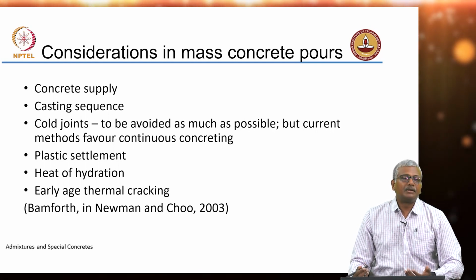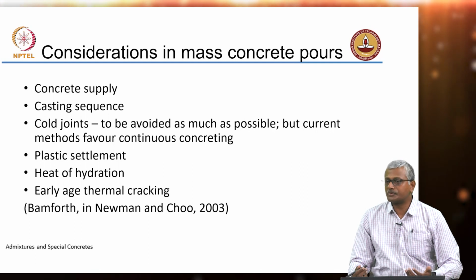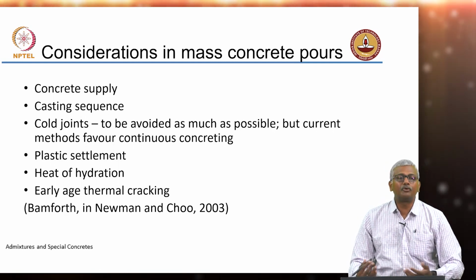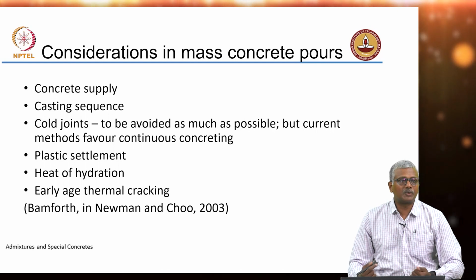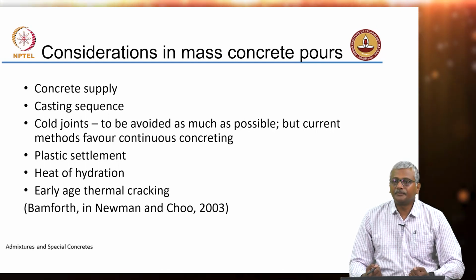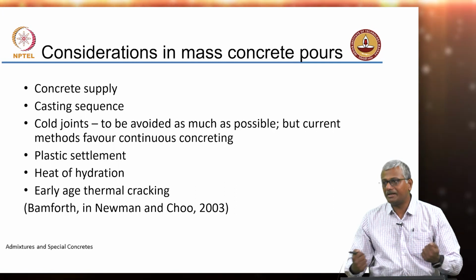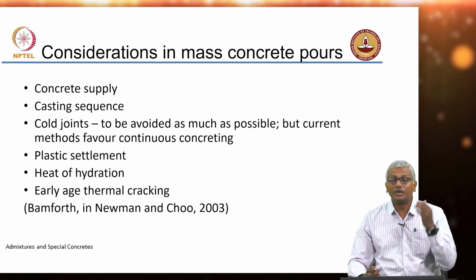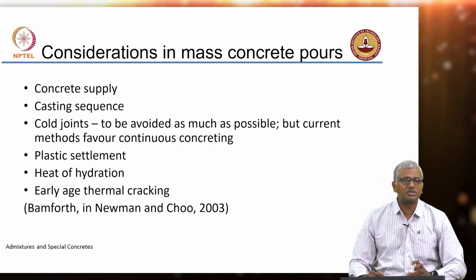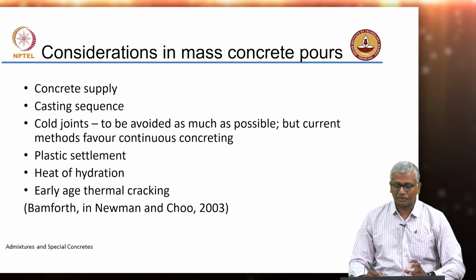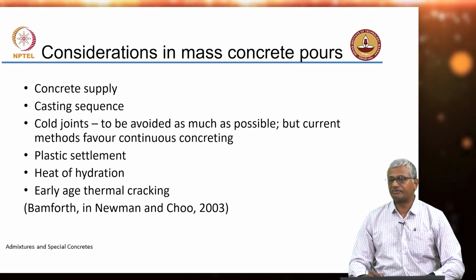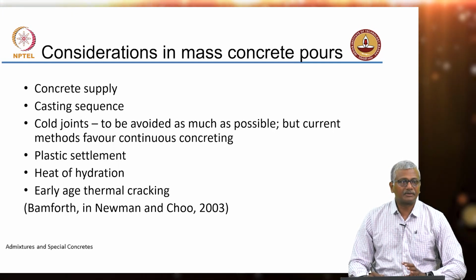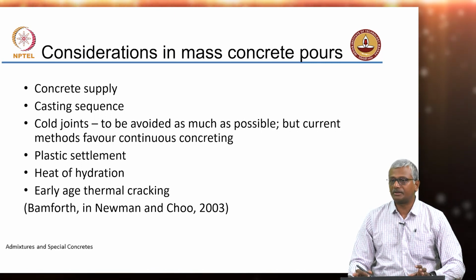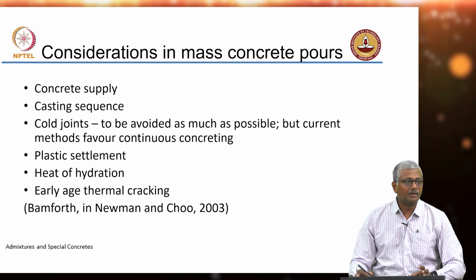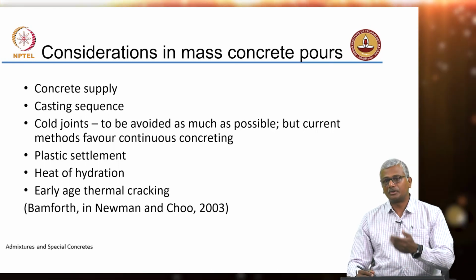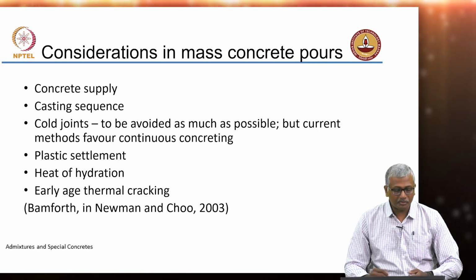In some instances, depending upon your concrete supply, avoiding cold joints may not be possible, but then in a reinforced structure, there is sufficient reinforcement to act as the shear key or binding between the different layers of concrete. So, in reinforced concrete, you do not really have to worry too much, but then still you need to avoid it as much as possible. So, today's methods essentially favor continuous concreting. That means, whatever be the size of the concrete raft or mass concrete that you are doing, you continuously supply the concrete to finish up the entire concreting operation.